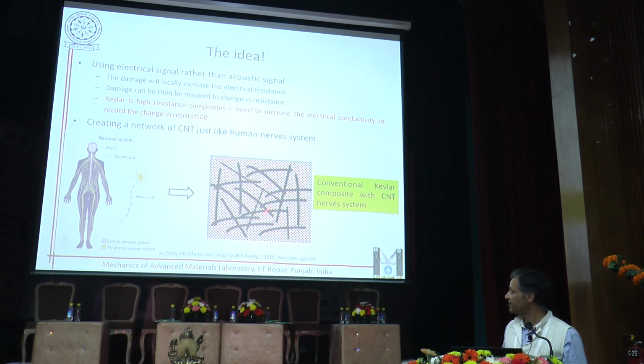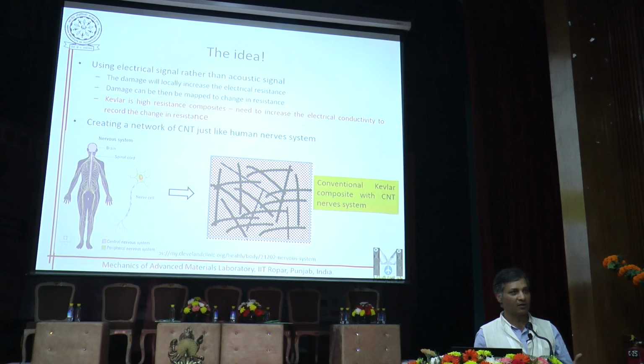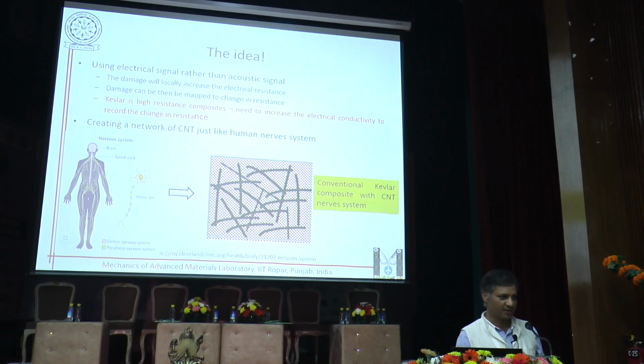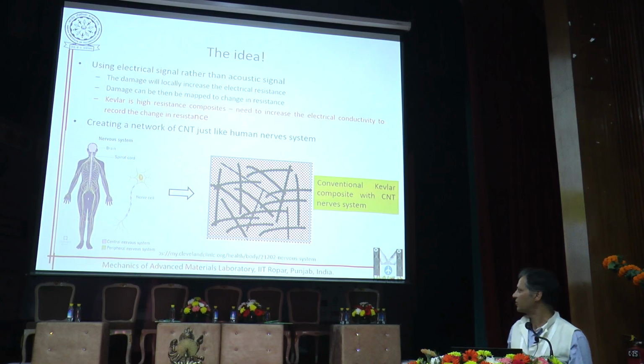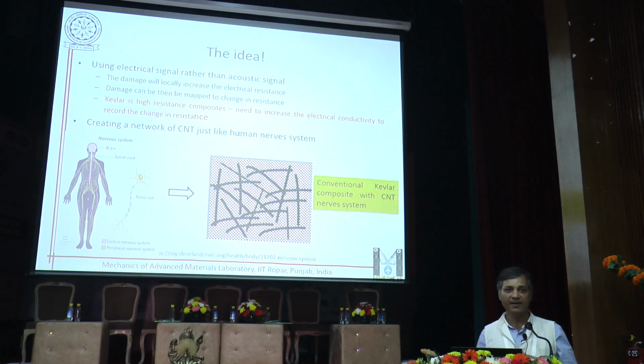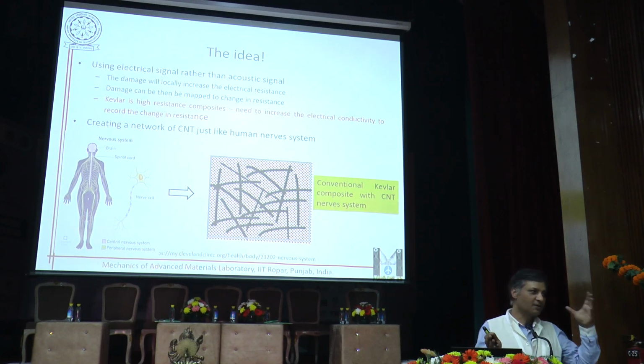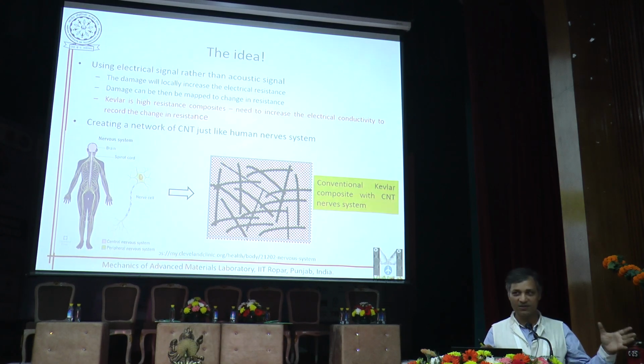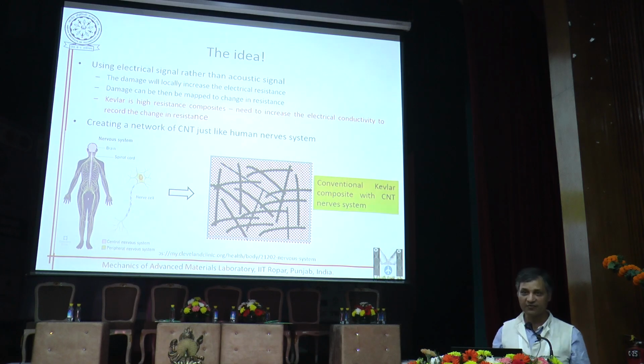So we can create a sensor network within the Kevlar composite using CNTs, and then we can do the voltage measurement and the conductivity mapping, and all sorts of things that we can do to map the change in the resistance to the size of the damage, location of the damage, and all other parameters which are associated with the damage, right? Okay. So basically this is what we were trying to create.